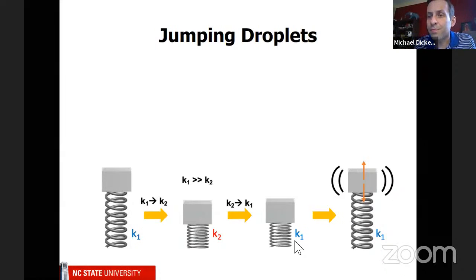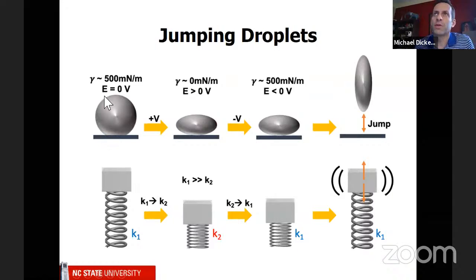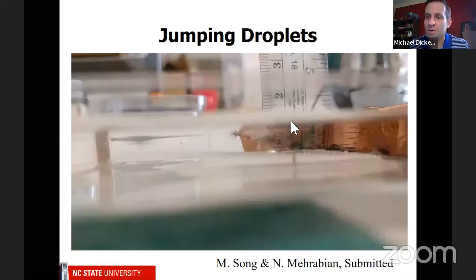Well, in our case, it's not easy to change a spring constant, but we go from a droplet that's at about 500 millinewtons per meter at 0 volts. We apply a voltage and we make the tension about 0, so that causes it to squish. We then can very quickly apply a negative voltage and remove the oxide layer and cause it to go back to 500. So that's like making the spring constant high. And then when we do, it's got this excess energy. So it's spread out at a large area, but it's got a really large tension. So now it's going to come back together and jump. So let me show you the results.